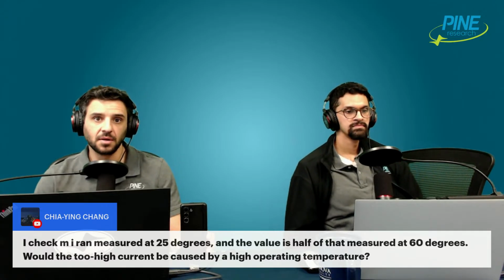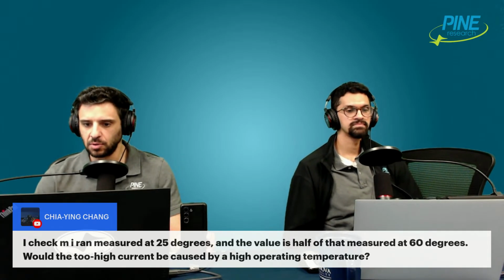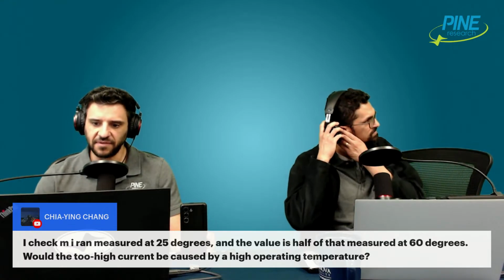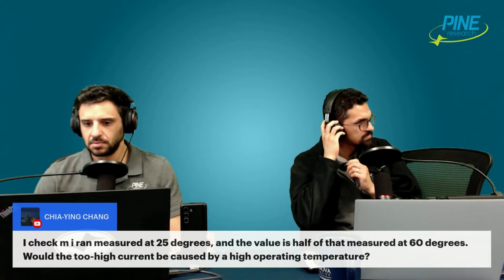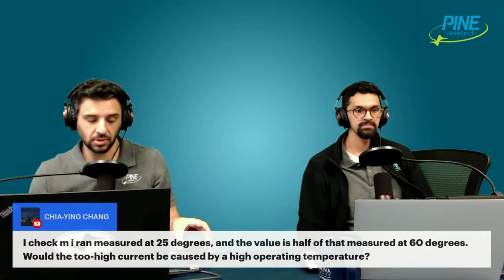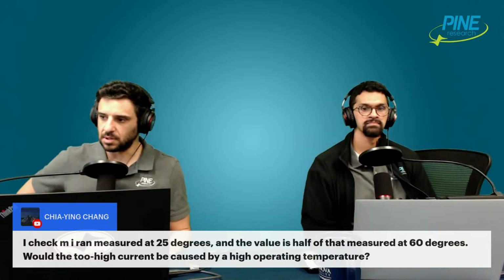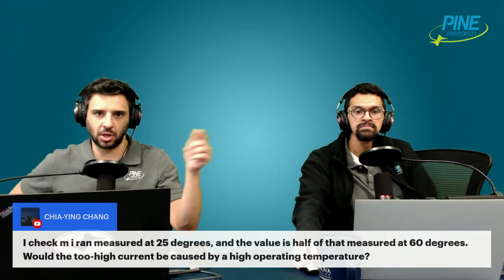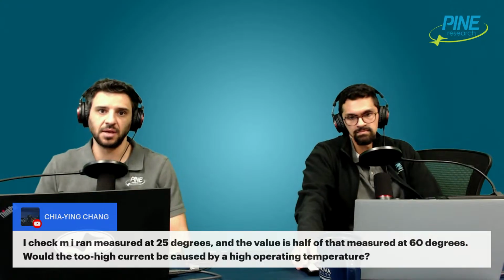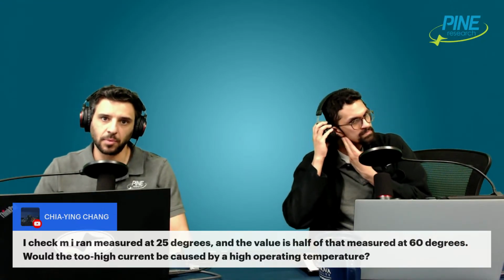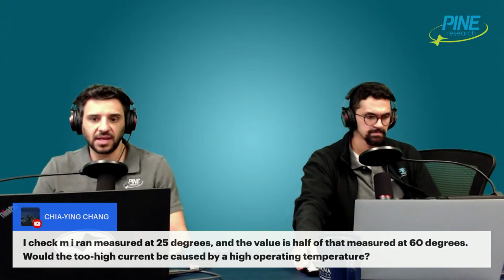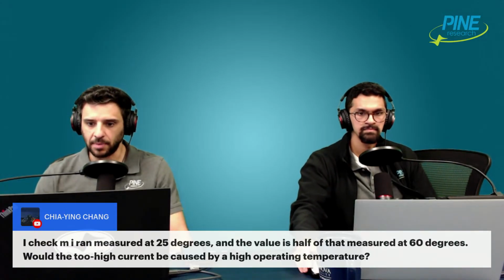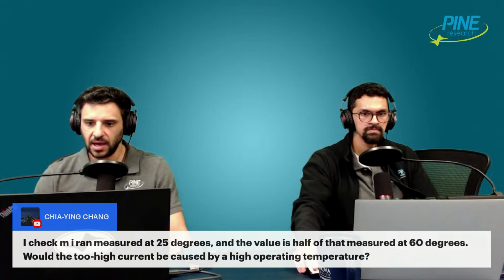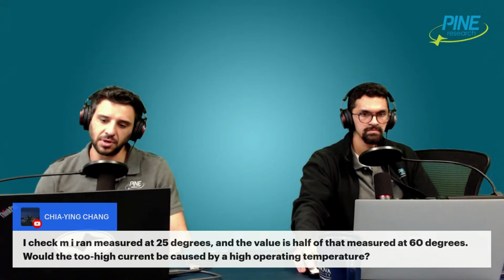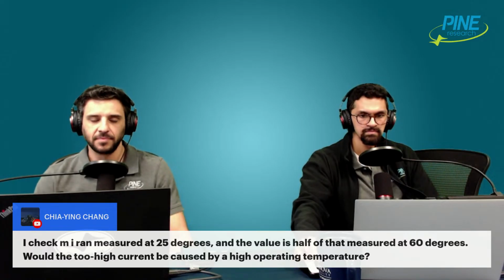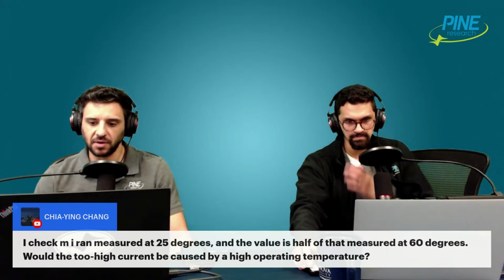The performance is better. I have no clue whether to verify 25 to 60 is double. That sounds fine. That sounds reasonable, to be honest. I don't know the rate at which the current goes up, for example, but absolutely at higher temperatures you're going to get better performance, which means more current. So I don't think that's unreasonable at all. If you need to do some conditioning at 60, you might have to back it off a little bit if you're overloading your potentiostat, for sure. I think that's most probably what you're finding.